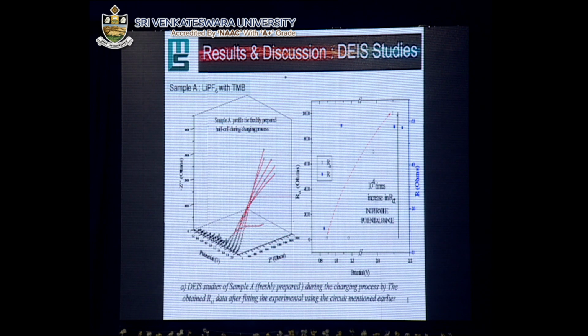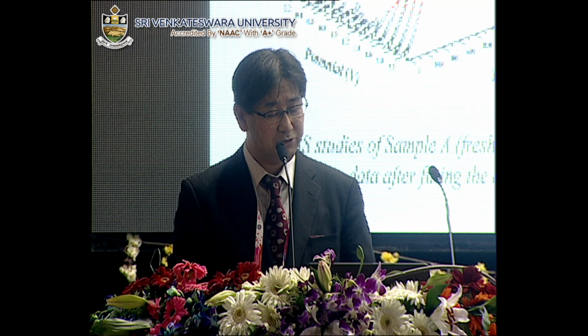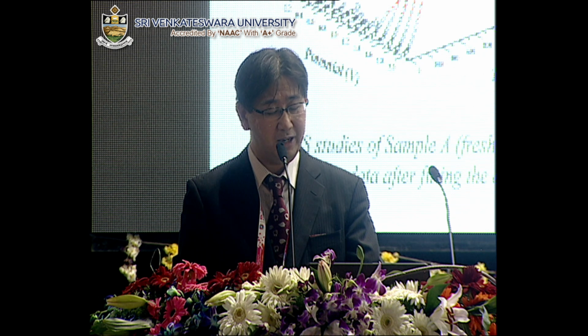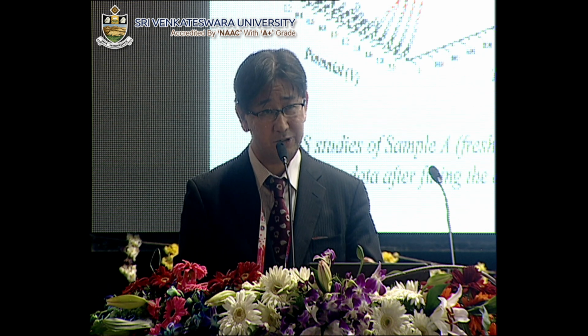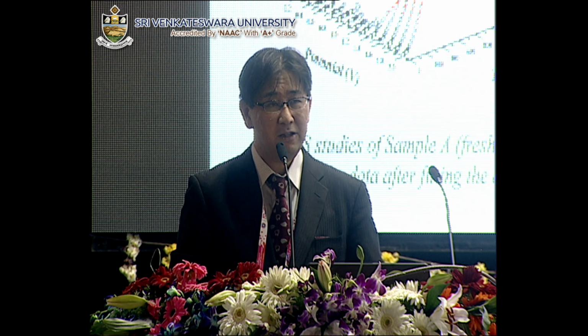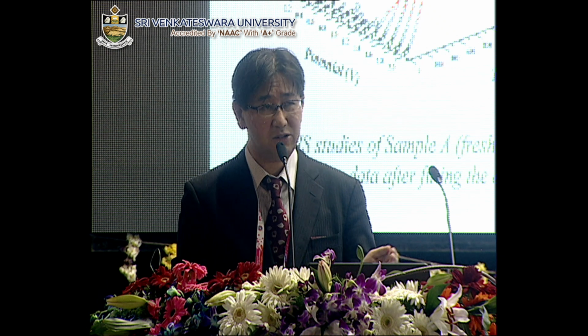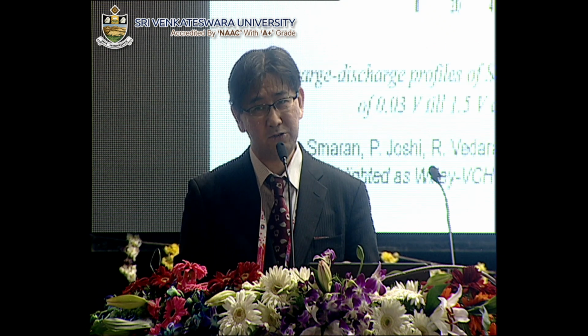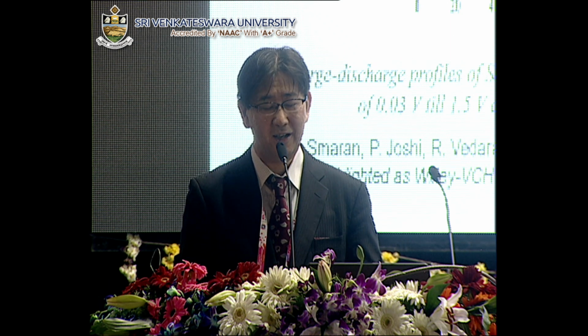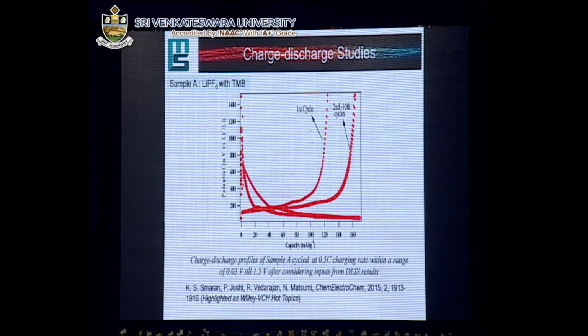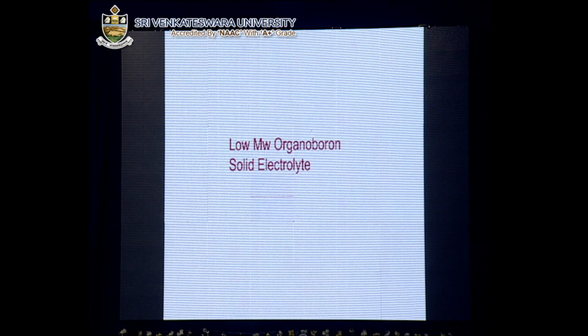So in this manner, we measured the behavior of one of the anodic half cells fabricated, and we obtained this kind of profile. And from this profile, you can see that when potential grows higher than 1.5 volts, for the first time, some tails grow due to the interfacial resistance. So this indicates the cutoff potential should be set at 1.5 volts. And after revising the cutoff potential accordingly, we observed highly reversible and beautiful charge discharge profiles. And in this manner, we have attained successful charge discharge utilizing the non-flammable solid electrolyte systems. And the next topic is a low molecular weight organoboron solid electrolyte.